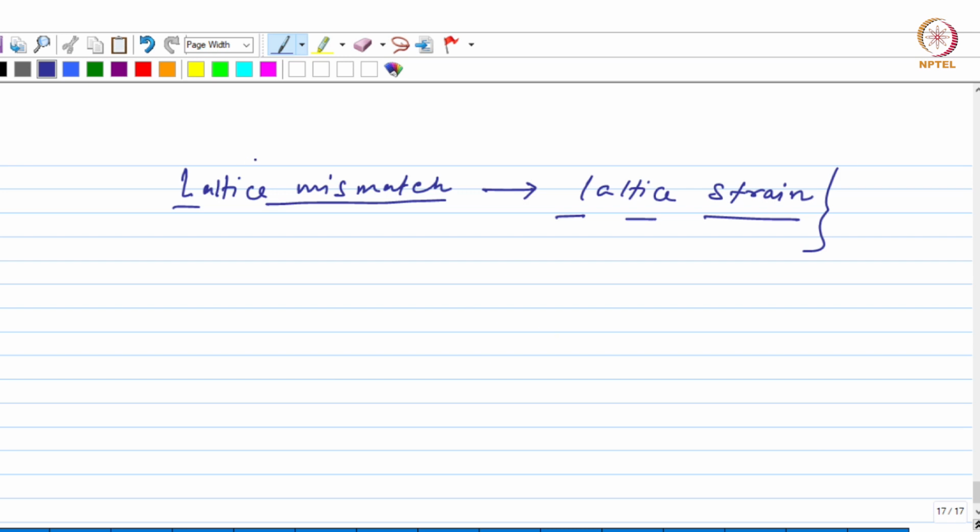The same goes for this precipitate theta prime. These kind of precipitates are known to be coherent precipitate, meaning that this will try and match with the lattice of the parent metal. Okay, although their lattice is different from the parent, because this is a different phase altogether, but they'll still try to maintain a coherency with the parent matrix, and therefore it will create some kind of strain around these precipitates.